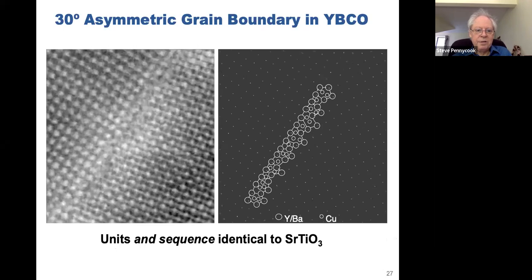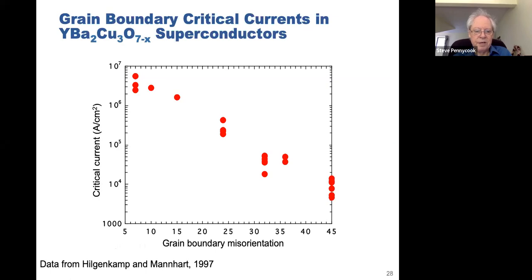Now, at this time, there were these intriguing results on grain boundaries and critical currents coming out of Germany, Hilgenkamp and Mannhart, for example. They were plotting the critical current across these bicrystals as a function of orientation. And they found that it went down exponentially. So grain boundaries were an absolute disaster for superconductors.